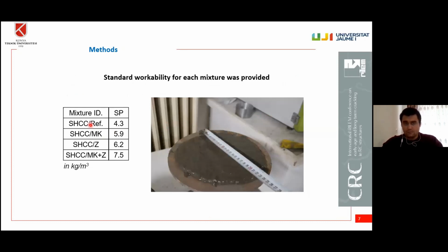As you see, the mixtures have different Blaine fineness, so it is difficult to use a constant amount of superplasticizer. Therefore, we aimed for a flow diameter of about 15 centimeters for each mixture, and we then defined the superplasticizer amount for each mixture.